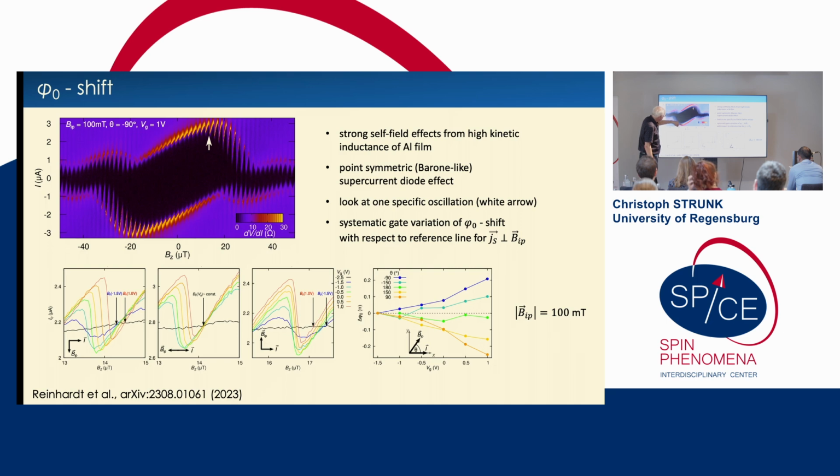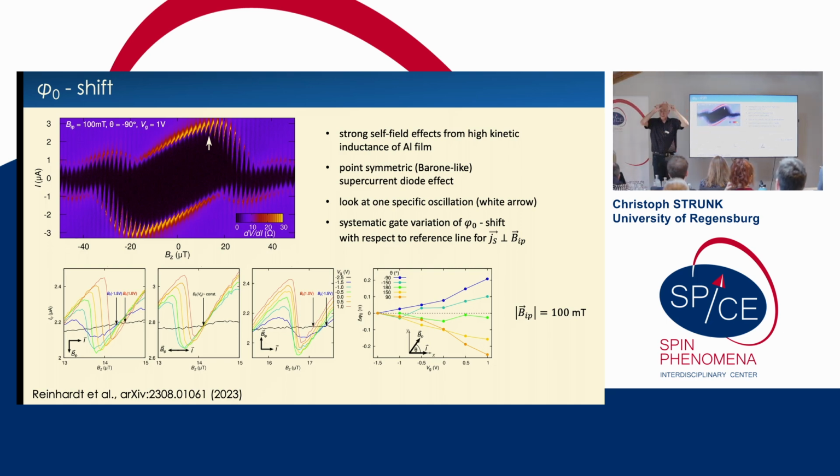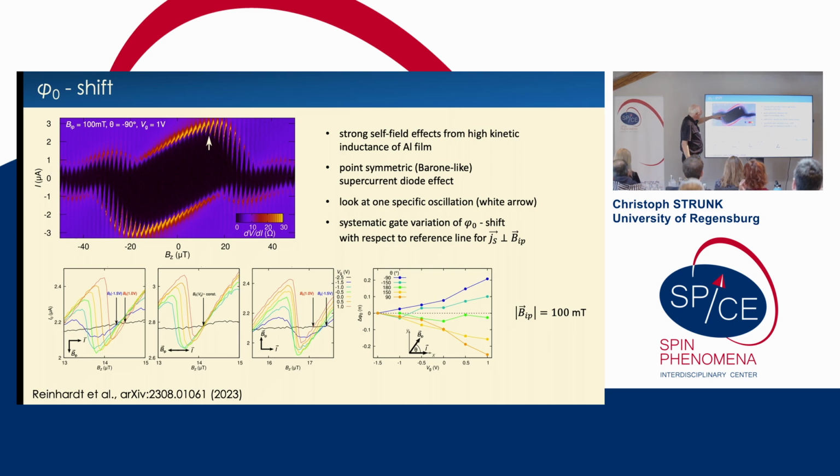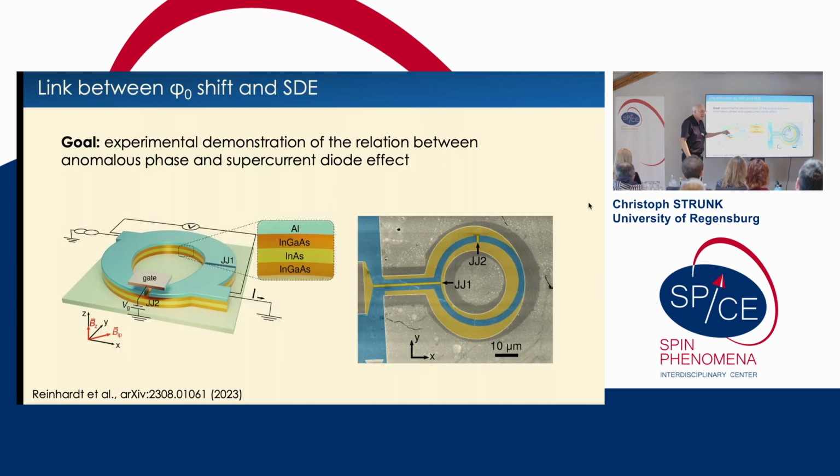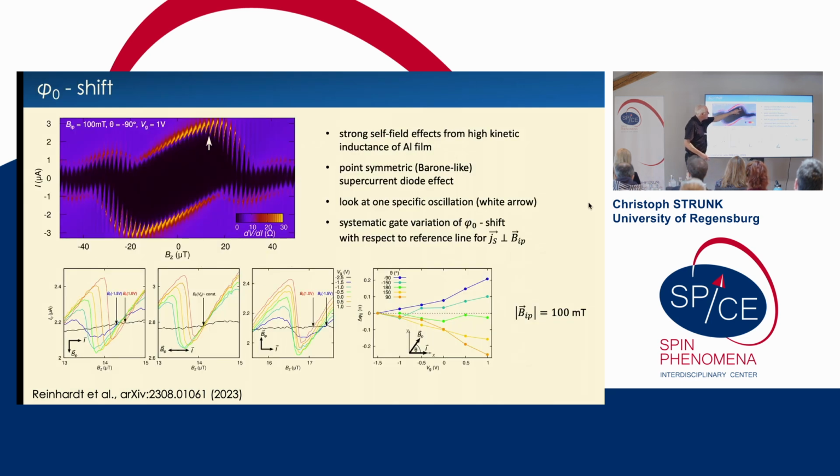And then you see oscillations which are coming from the periodicity of the loop of the SQUID. Okay? And actually what you see here is mainly the critical current of the large junction now modulated with the critical current of the small junction. Because, depending on the flux that is enclosed in the SQUID, the two currents are either opposing each other or going parallel, with, of course, all intermediate values in between, and that produces these oscillations.